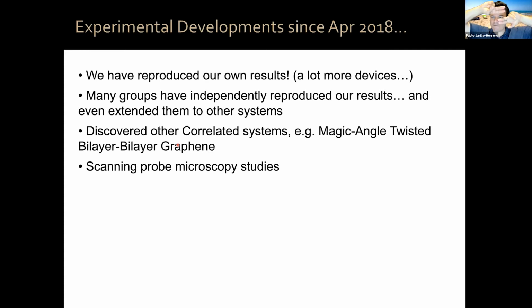Okay, so we now have in total 4 layers of graphene, 2 with no misalignment, 2 with no misalignment, and then twisted pairwise with respect to each other. That system gives you interesting correlated magnetic states, for example.